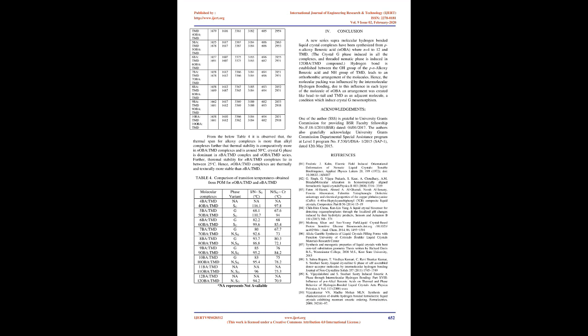In TMD with the proton accepting substituent COOH, the intramolecular H bond in TMD disturbs the symmetry of the amino group. Therefore, the intermolecular H bond with the acceptor substituent is formed by the free NH group. Stability of the hydrogen bonding is observed by the IR peak shift of the in-plane bend, IPB, mode of NH and CH towards the higher frequency side.